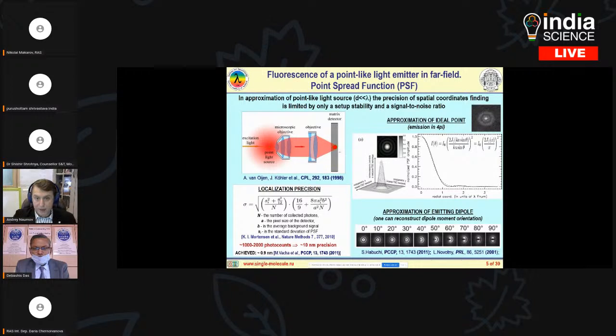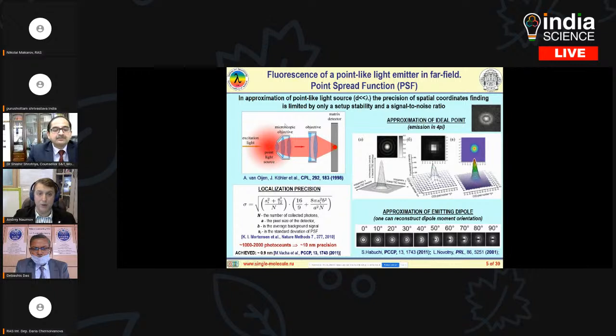If you have such an image, which you detect with a very sensitive CCD matrix detector, you can fit this image by a two-dimensional Gauss. Then you can recalculate the position of the point light source, namely this lateral position in the focal plane of our optical microscope. In this case, we are not limited by the diffraction limit. We can recalculate the position with precision limited only by signal-to-noise ratio. So, if we have a bright dye molecule, we can detect the image of this dye molecule, and then we can find the position with very high accuracy.